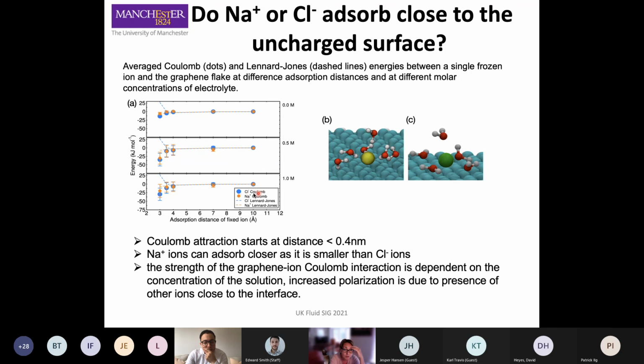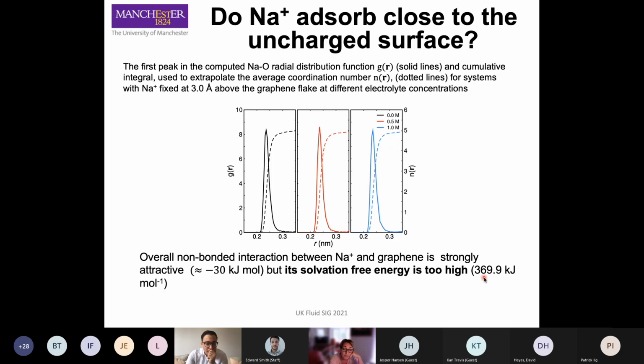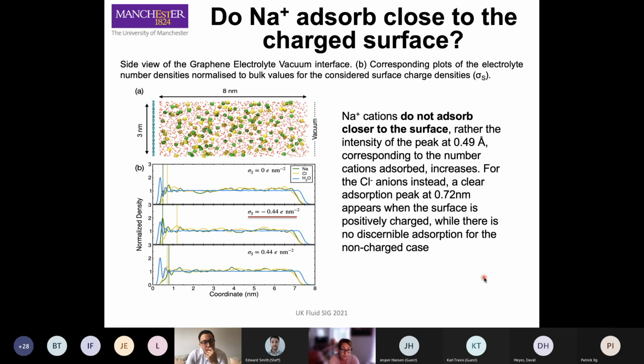But what happens is that in the case of chloride, which is much larger, there is the Lennard-Jones energy that, as soon as, from the electrostatic point of view, the ion is adsorbed, so it tends to adsorb, and there is a negative energy, a Coulomb energy, due to polarization. The Lennard-Jones shoots up, so the chloride will never really dehydrate. The sodium, however, should, because you can see that the Lennard-Jones is always negative. So overall, the adsorption energy is negative, but the ion doesn't dehydrate. And the reason is because sodium has a very high solvation-free energy. So in order to dehydrate, even for 1 molecule of water, there is the need of a very strong adsorption energy. So a full dehydration probably is not going to happen with neutral graphene.